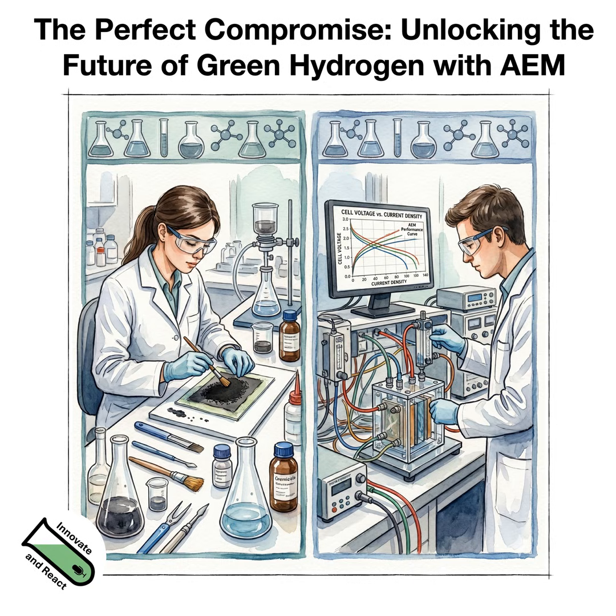So the membrane and the catalyst need to be in contact, of course. But in the PEM world, you really need to make sure that you have ionic pathways from your membrane to your active centers. In the AEM world, it's not so big of an issue, as Miriam already told us. There's always ionic conductivity due to the KOH that's abundantly everywhere in our electrolysis. And then it's a little bit easier, so we do a lot of spray coating, which is a quite slow process. And if you do slow processes on polymers that like to change their structure during the coating, then they shrivel up, for example, and then you get inhomogeneous layers. And oftentimes it's better to sacrifice a little bit of contact from catalyst to membrane to have it more homogeneously deposited on the PTL side. Okay. But it's still membrane, then the both catalyst layers, and then the PTL.